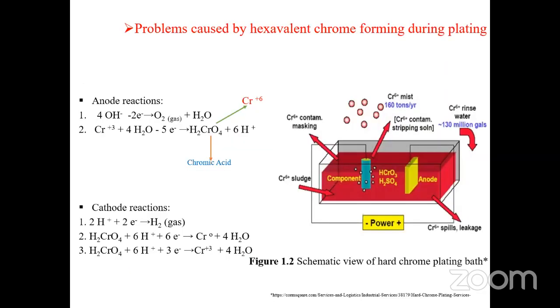In the plating bath, chromic acid occurs in the anode. And this chromic acid is a hexavalent chromium compound, which is known to be a human carcinogen, and the process is quite inefficient, producing large amounts of hydrogen and hydrogen bubbles. When these bubbles rise to the surface, the bubble bursts, throwing a fine mist of hexavalent chrome into the air.